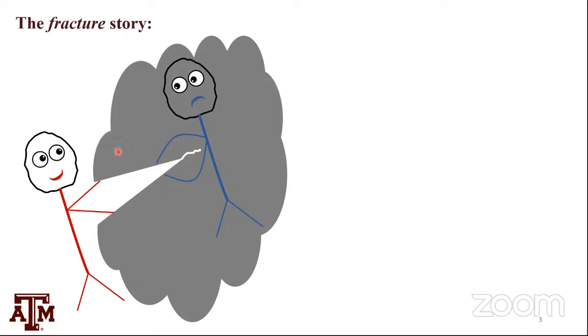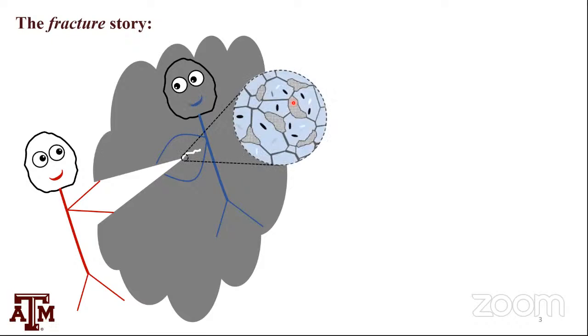The balance of two forces: one is the driving force, one is the resistance force. When the driving force overcomes resistance, the crack starts to grow. What's the big deal about it? Nothing much to know, other than the fact that materials are not this gray blob of a piece. Each material has a heterogeneous microstructure. And as you see, when we bring this microstructure in, both the good guys and the bad guys become happy, because the microstructure can help the good guy. The microstructure can also help the bad guy. A bad microstructure that nucleates damage easily will make the crack grow easily. A good microstructure, where good and bad remain qualitative and debatable, but we'll just go with it, can also help the good guy.